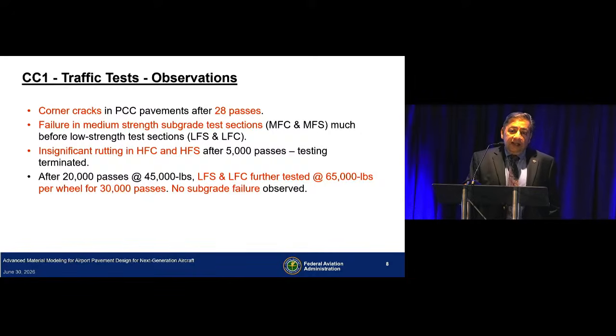So we started testing, and these pavements were designed for 10,000 passes. Concrete pavements had corner cracks in 28 passes. That was shocking. We stopped testing, and we had to do a lot of work on concrete pavements to figure out why that happened. Once we determined that, we continued testing on our asphalt pavements. Again, they were all designed to fail in the same number of passes, but medium strength subgrade sections failed much earlier than the low strength sections. That was very shocking for us too. And in the high-strength subgrade sections, we tested till 5,000 passes and did not see any significant amount of distress, which was rutting. So we stopped testing on those sections.